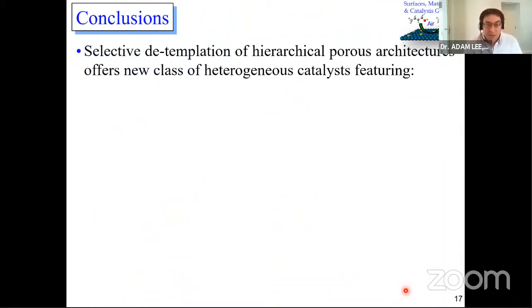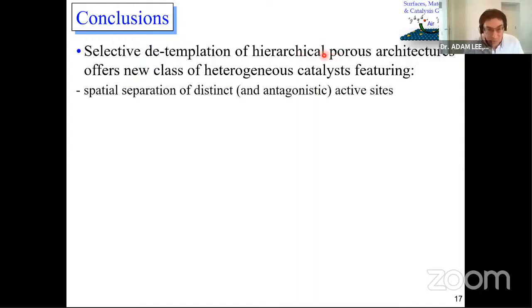Hopefully, I've shown you that by using this selective detemplation approach, you can make hierarchically porous materials, which is a common, well-known thing, but it's not well known that you can actually locate different types of active sites in different parts of the catalyst. So we've shown you spatial separation of distinct active sites, for example, platinum and palladium. And I've shown you that these active sites could actually be active sites that don't like each other. They could be antagonistic, which is the case for an acid and a base. These are active sites that must not meet each other, otherwise they neutralize. And that's been achieved by using this selective detemplation.